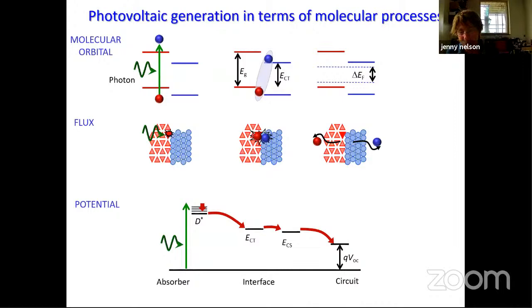The charge separated state. So typically, I would say, when you go from charge transfer to charge separation, if you don't have any difference in microstructure of a material, I mean, there's other things that might influence. There might be some local gradient in energy levels that would actually stabilize charges when they separate. If you don't have that, then one of the important things will be the density of states. So when you have an electron and hole tied together at an interface, they are there in one configuration, but there are many ways in which they could separate. And the fact that there are many ways in which they can separate is tending to push down the free energy of the charge separated state. And that's one thing that would assist.